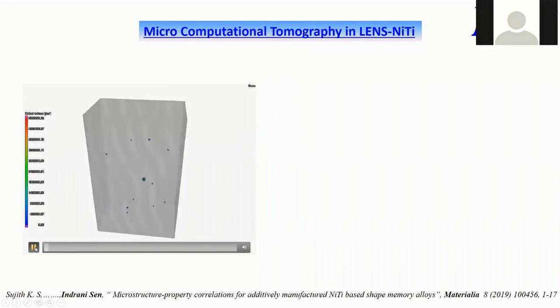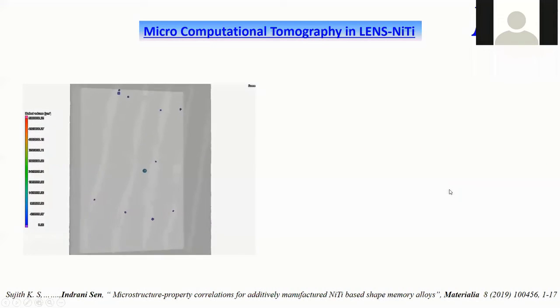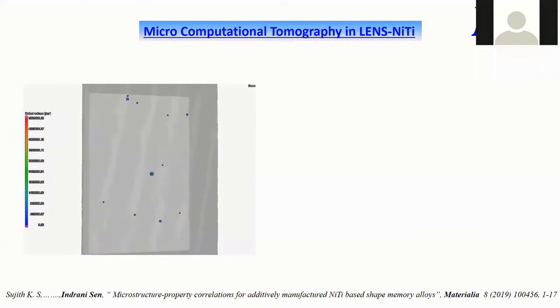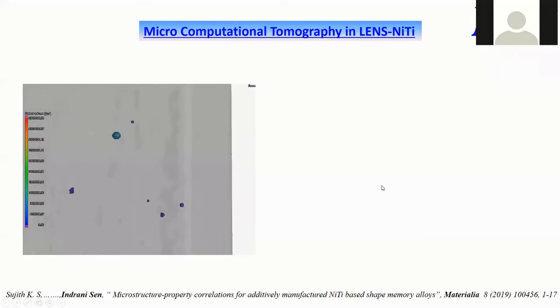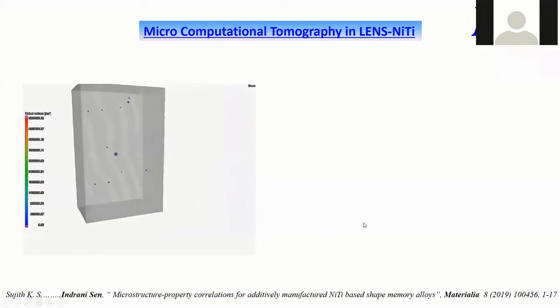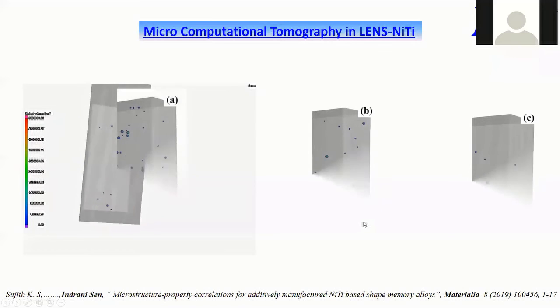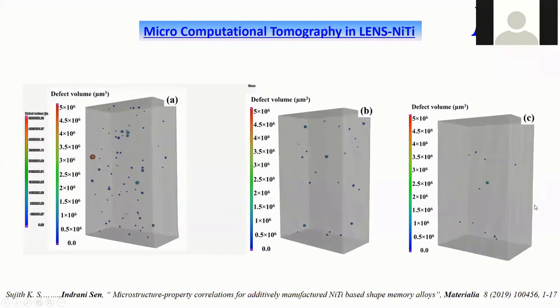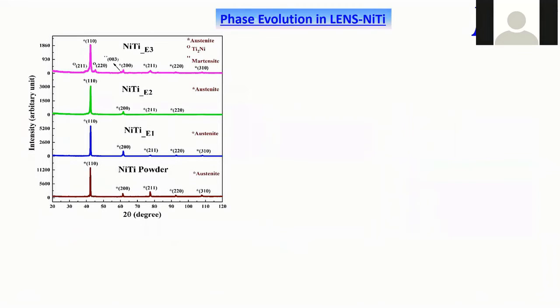And this one just shows the porosity inside the structure that is forming because of the direct printing. That can form some porosity, and we have done the 3D analysis of the pores that are forming. And this is done for all the three alloys. You can very clearly see from here that the alloy prepared with the lowest energy density has quite some pores or unmelted parts, while the one prepared with the highest energy density is mostly devoid of such big pores.